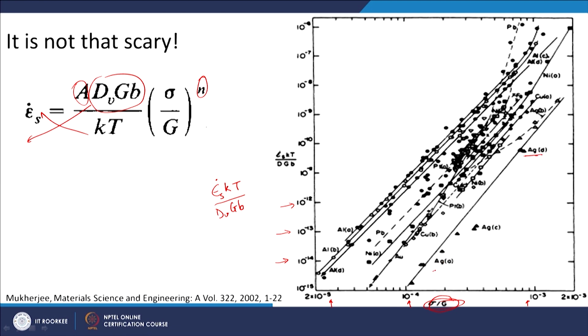And you can see here a lot of different data is plotted. So, you have silver, nickel, lead, I think aluminum, and then of course aluminum here, nickel here, aluminum here, copper here. A lot of data is plotted on a single band of curve, and through the slope I will be able to get the parameter n, and from the intercept, I will be able to get the parameter a. So, this is how I would be able to get the constitutive equation for a creep kind of deformation.